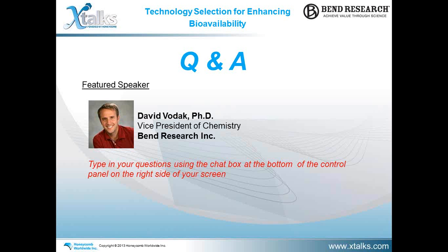Where it gets to on the suspension preparation is you have to understand where your failure modes are. If you have a really low Tg dispersion and you put it into a suspension, the water ingress can potentially cause phase separation and crystallization inside the particle because you have mobility. On the other side of things, if you have reasonably high solubility in your aqueous media, or especially if you're putting in things like surfactants, you can leach drug out, and now you run the risk of ripening. So depending on what problem you're trying to solve in the suspension preparation would drive what you use. And I'll just say, in really desperate cases, we've done things like try to make suspensions in olive oil, but that's certainly the exception rather than the rule.